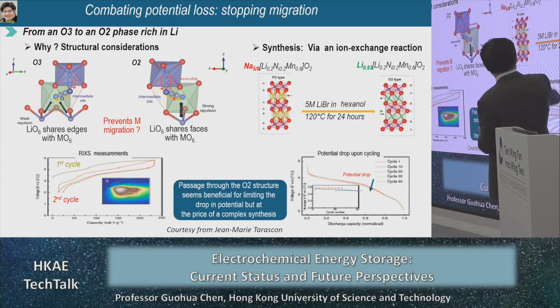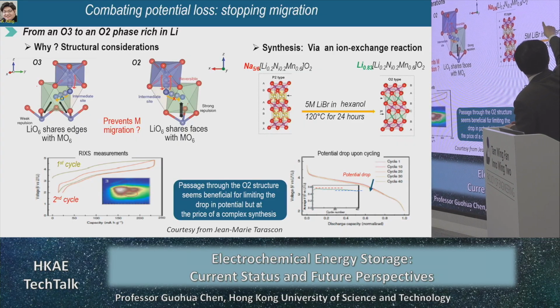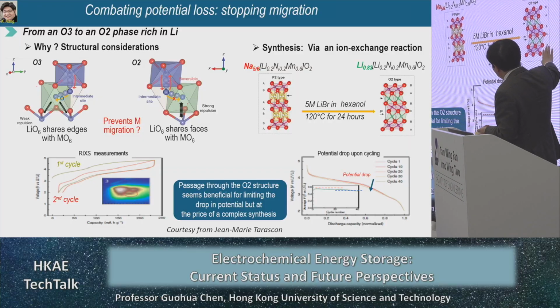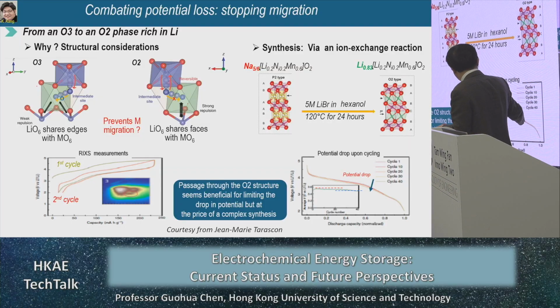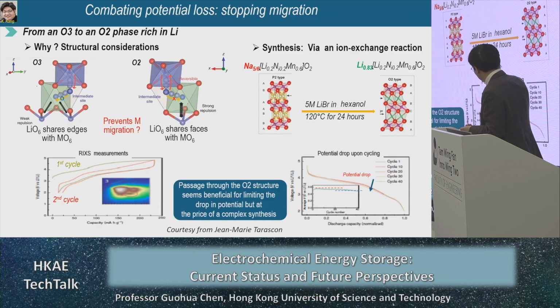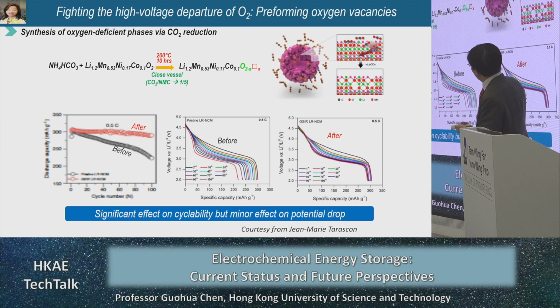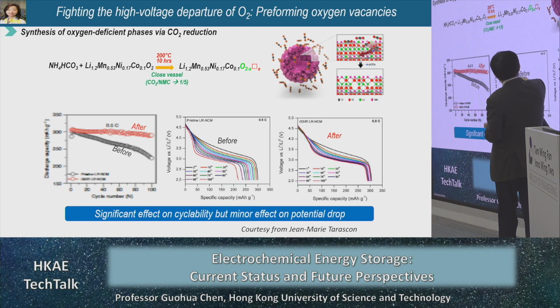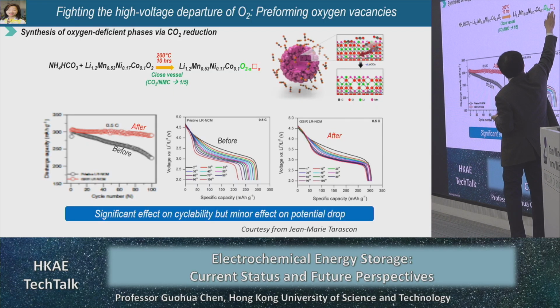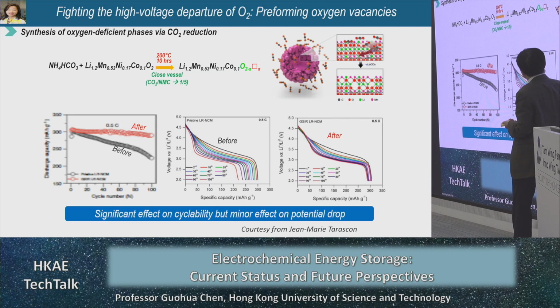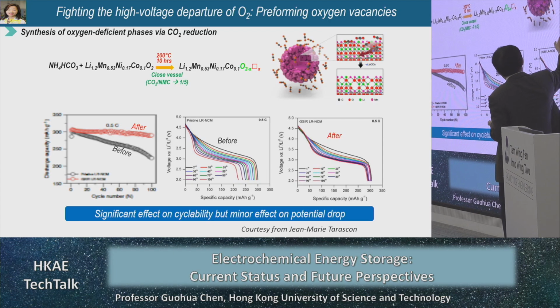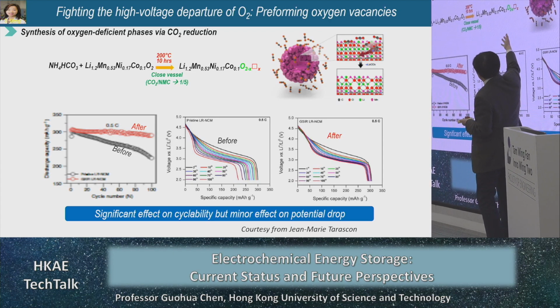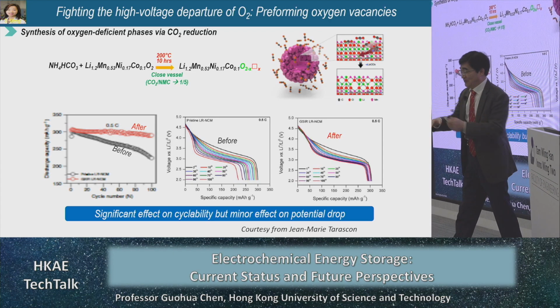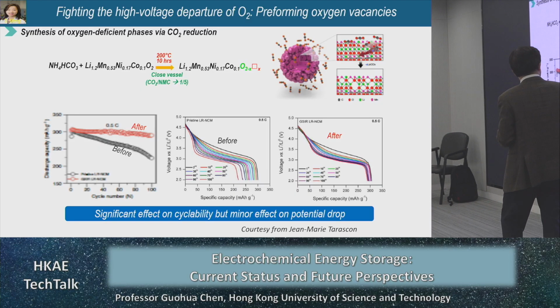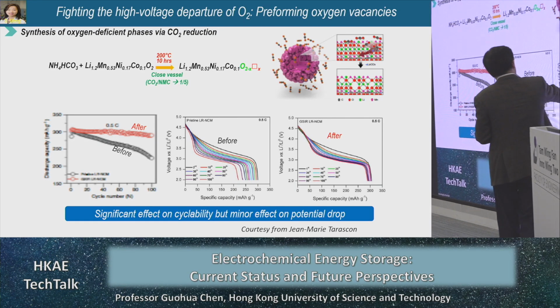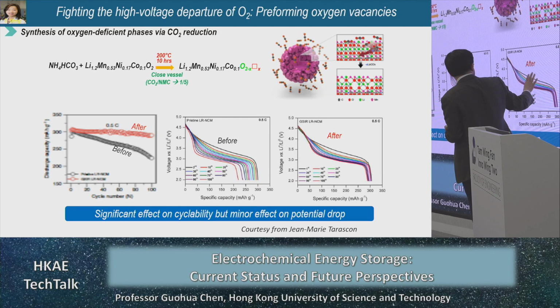There are some ways to overcome this, but of course, it's not perfect and not ready for industrial deployment. For example, we could synthesize using an ion-exchange reaction, and that could make the cycling more stable. Or we could have a precursor with this oxygen deficiency. And when oxygen is released, the deficiency part will take it, so it will not have the structure change. Before it's like that, afterwards it's like this.